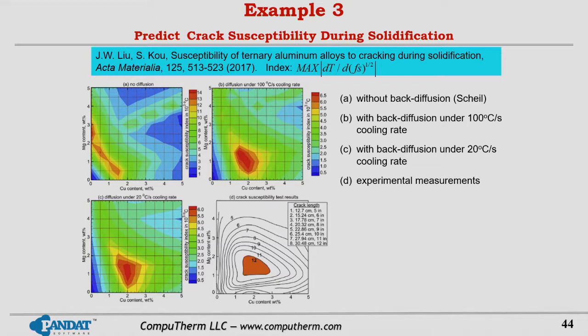In these four figures shown in this slide, the bottom right figure is experimental data. The area shown by the orange color is the area that's most vulnerable to cracking during solidification. If you take a look at figure 1, the top left figure, that's the simulation we did using a cell model.